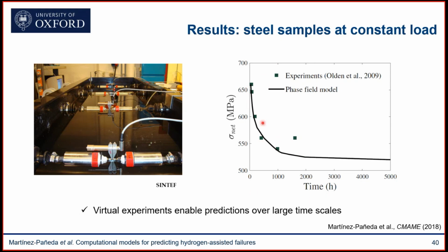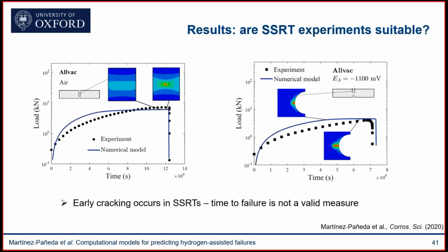But we can take our model and not only reproduce the experiments, gaining confidence in our predictions, but also run virtual experiments over very large timescales, which allows us to determine the remote stress threshold below which embrittlement will not happen. So this is another ability of the model. We can run very large experiments, either large in time scale or space scales.